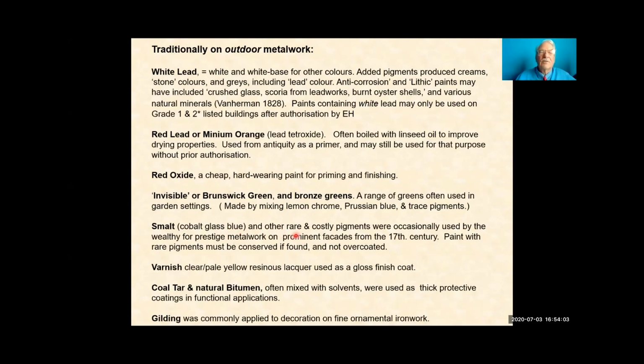So if you find this, you really do need to retain it. It's a lovely dark blue color. And it's a fairly rare pigment, so you must retain it, conserve it if you find it. Varnish is a clear-ish pale yellow lacquer, which was used to put on the surface to protect the substrate and give a gloss. You'll often find tanks and pipes covered with things like coal tar and natural bitumen.